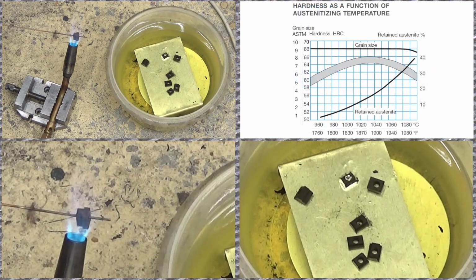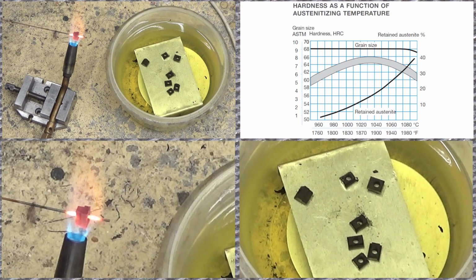In this curve you can see that there is an optimal value for austenitizing temperature. For Sverker 21, that temperature is 1030 degrees Celsius. The temperature I can obtain using this butane torch is around 1100 degrees Celsius. I keep the workpiece in the flame until it has reached its maximum temperature. I do not hold it in the flame for the required 30 minutes, that would be insane. It seems to become hard enough, even with a short exposure to the austenitizing temperature.